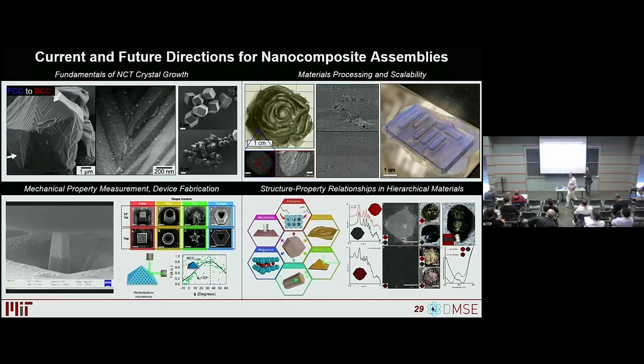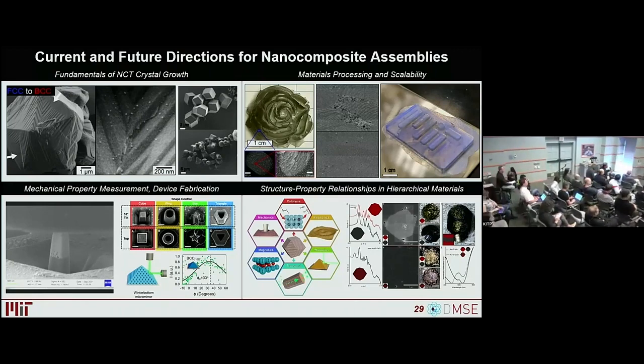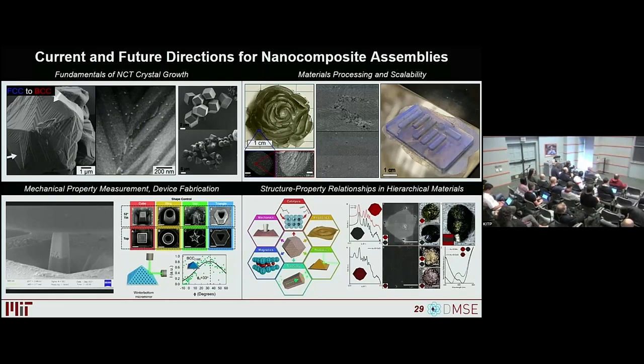Yeah. So if I look at your hexapod system, or hexapod, is that what it was? Hexapod. Okay, hexapod. Yeah. You concluded, if I got you correctly, that it wasn't reminiscent of atomic scale systems. But to me, it looked awfully similar to using seeds in the fact that vertices and different faces are energetically more active than others. And if you control the chemical potential of the solution, you can selectively grow first off vertices, then off specific faces, and then off the more stable faces. That's commonly used to evolve shape in nanocluster synthesis. Yanwei Li's got this where you can make any type of structure you want. So why isn't that the explanation for that?